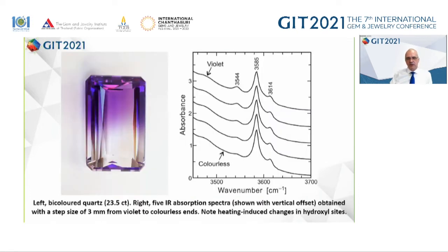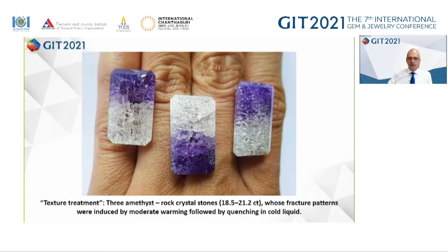This stone used to be an amethystous colored quartz, faceted, and after one-sided heating, it is decolored. So on the bottom of this picture, we can see the heating-induced color change by a change in the occupation of hydroxyl sites in the lattice. The area integral of these bands is about the same, so there is no water or hydroxyl loss, but there is a change in the occupation of sites, so some moderate or minor structural change. Yeah, and this brings me now to the last example.